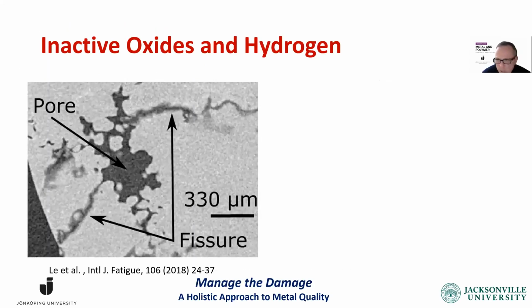I came across this in fatigue literature, something they call fissure. Here's a pore. There is what they call fissure, and when you read fatigue literature on aluminum castings, they say, oh, the cracks start on the first cycle. It's not a fatigue crack, it's the damage, it's the bifilm that's opening up. And simply because pores are surrounded by bifilms that have not opened up, the damage is much more extensive.